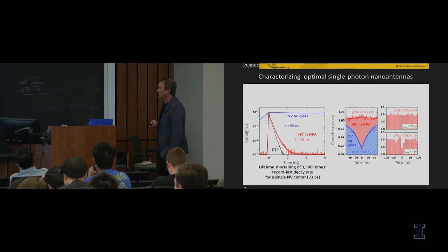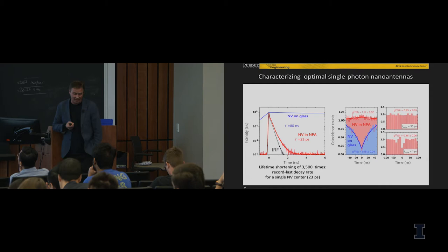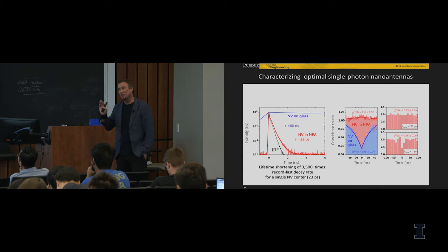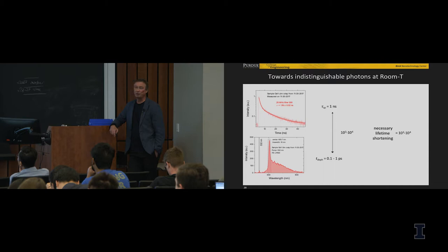But the truth is, with nitrogen vacancy, decoherence is crazily high because of coupling to phonons. Because of the symmetry, the decoherence rate in that case is so high that even with all the enhancement we are doing, it's hard to beat. So we probably don't want to try to beat decoherence in that system. We want to look at other ones, and that's what we are still looking for: a good quantum emitter with a reasonable decoherence rate at room temperature.